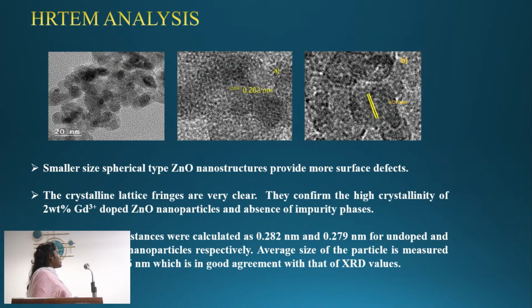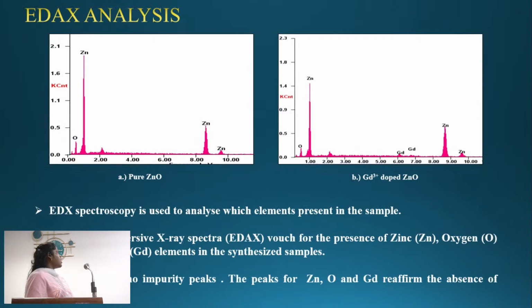The next one is HRTEM analysis. It clearly shows that small spherical ZnO nanoparticles provide more surface defects. The fringes are very clear and it confirms that gadolinium-doped ZnO is in good agreement with XRD. The interplanar distances were calculated as 0.282 nanometer and 0.279 nanometer for undoped and gadolinium-doped ZnO nanoparticles respectively. The average particle size is 20 nanometer for undoped and 18.6 nanometer for gadolinium-doped ZnO. And the next one is EDAX analysis.